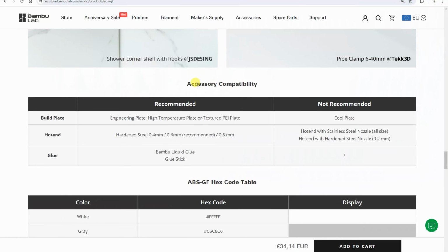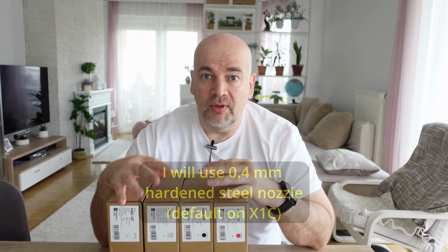And the second is unfortunately the layer adhesion, which I already mentioned that I experienced, because these fibers will actually reduce the cross section. They are not long enough to help those layers hold together, but I hope the difference will not be too big. Don't forget, because of those glass fibers, it is recommended to use some kind of hardened steel or similar nozzle, because the regular brass nozzle may wear out too quickly.